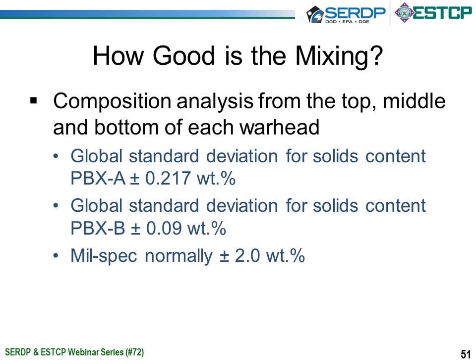The second plastic bonded explosive that we did this experiment with is a much more fluid material. It's got an end-of-mix viscosity that's probably closer to 1 to 2 kilopoise, whereas PBX A is closer to 20 kilopoise, so an order of magnitude or so drop in material viscosity. Again, the same experiment, three warheads on that warhead holder that you saw in the previous slide. Sample the material top, middle, and bottom at the end of the mix. This mix process takes us about 6 minutes to put this material together, and you see there that the global standard deviation is very, very small, less than a tenth of a weight percent.